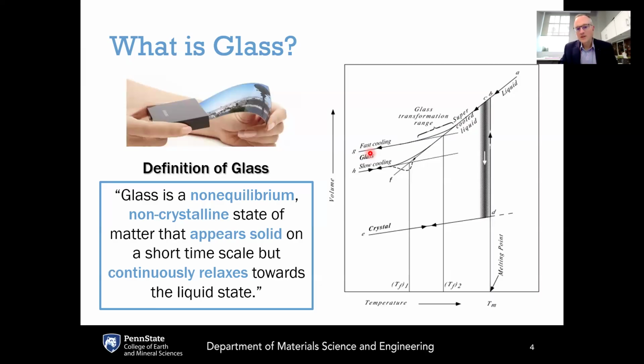Now, one of the interesting things about glass being a kinetically frozen non-equilibrium material is that the properties of the glass, like molar volume, depend not just on the composition of the glass and the temperature and the pressure, but also the entire history of how the glass got to that point. So you'll notice here two curves, one for fast cooling and the other for slow cooling. If you take a supercooled liquid and you cool it really fast, then you're giving that supercooled liquid less time to stay in its metastable equilibrium. And as a result, the glass transition happens at a higher temperature range.